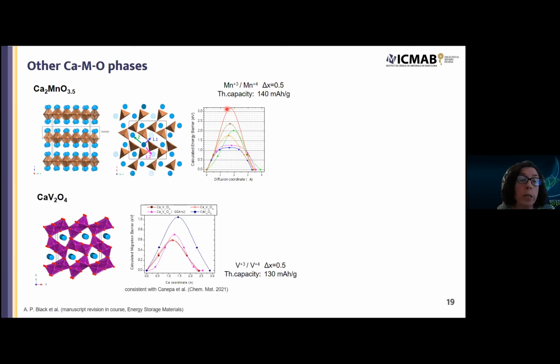And another compound with which she came was calcium V2O4, which has a very similar crystal structure to the manganese phase that we had been studying before. And in this case, she found that the migration along the tunnels has very low barriers, about 0.5 electron volts. And if we were able to extract almost all calcium from the crystal structure, then the barrier would be a little bit higher, but still those were considered interesting for electrochemical investigation. And also in parallel, works by the group of Piero Canepa in Singapore came with similar values.